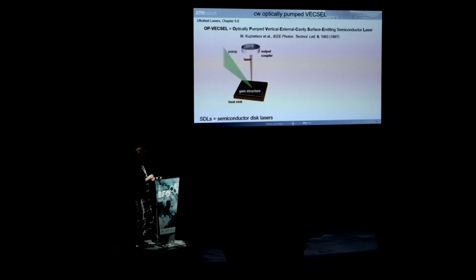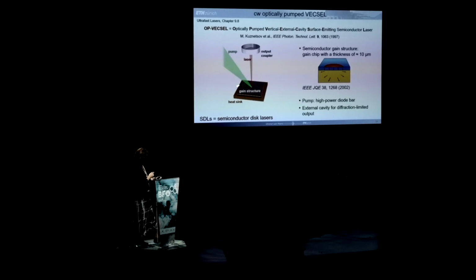Instead of having an ion-doped solid-state laser like a ytterbium-doped or Ti-sapphire laser, it is an optically pumped semiconductor laser. You have a quantum well gain structure, anti-reflection coated, and then going to the output coupler. With optical pumping, you can scale the power of these lasers by simply changing the mode size, because the gain chip is only around 10 micrometers thick. If you open up the mode size to larger, you have a one-dimensional heat flow, and you can effectively take the heat out of this laser. That's why this is also called a semiconductor disk laser, because the active region is so thin.